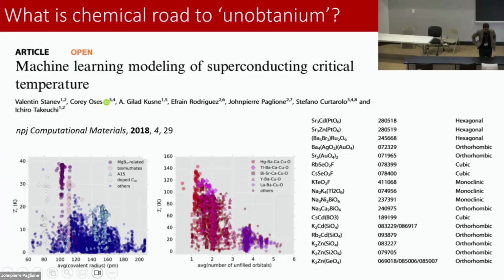Yeah, that's a very good question, and I don't know if I'm going to sound like an alchemist in my response, but when I told one of my students, Chris, I don't know if Chris is here, we made these chalcogenides that are Mott insulators. And I was like, Mott insulator, dope that thing, see what happens, right? And so we did the liquid ammonia experiment, and I said, let's do 15%, because with electron doping, I guess hole doping too, well, at 15%, you get this nice optimal Tc in many cases. So it's just intuition by looking at what's happened before when it comes to electron or hole doping levels as to what we'll get. Unfortunately, we haven't gotten a superconductor yet, but one of the things I start thinking about is what the phase diagrams look like for the superconducting domes of other known systems, other Mott insulators, for example, and then we target there and then start moving maybe 5% away from that to map it out.